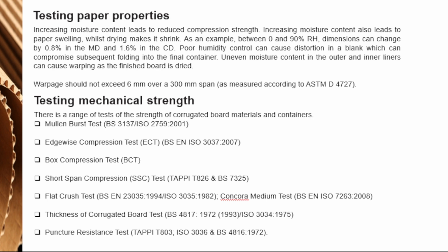Increasing moisture content leads to reduced compression strength. Increasing moisture content also leads to paper swelling, while drying makes it shrink. As an example, between 0 and 90% relative humidity, dimensions can change by 0.8% in the MD and 1.6% in the CD. Poor humidity control can cause distortion in a blank, which can compromise subsequent folding